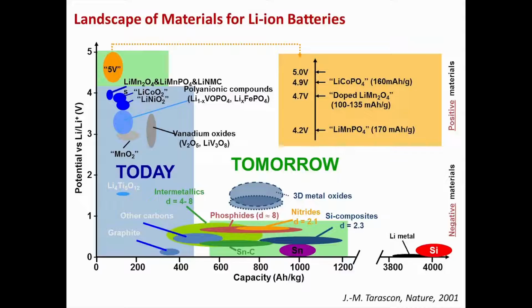But as Chini talked, it comes with a lot of problems. One of the main problems is its huge volume expansion and contraction, which results in surface instability. So if there is any kind of layer on the surface, it is going to go through a lot of stress. Due to that stress, the SEI could get affected or damaged, and that is one of the big issues which could result in continuous degradation of the electrolyte and continuous SEI formation.